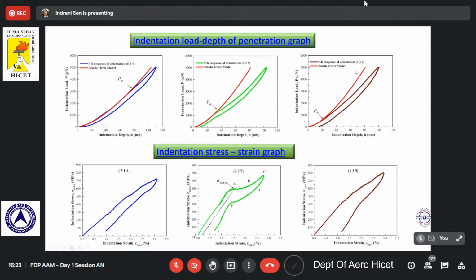This becomes more apparent if we are able to find out the stress versus strain curve. You can see that it shows some features similar to the pseudoelastic behavior. There is a plateau strain and there is some further deformation as well. But here there is a huge amount of strain that is not being recovered at all. So that means that the different orientations will behave differently.